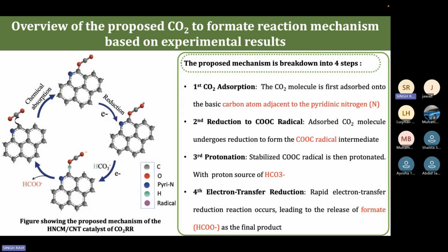Thank you so much for a nice discussion. I have one comment about that. Basically, this is derived from the ORR mechanism, Ravi. Yes. So basically this is a nitrogen, and this nitrogen withdraws the electron from the carbon, and then this carbon has a deficiency of electron, and then this oxygen can donate electron to it, and it can be absorbed here. So in a transition metal, we have a 3d orbital splitting, and then bonding and low energy and high energy molecules have their own functions. But here, this adsorption is purely based on the electronic structure and electronic density.